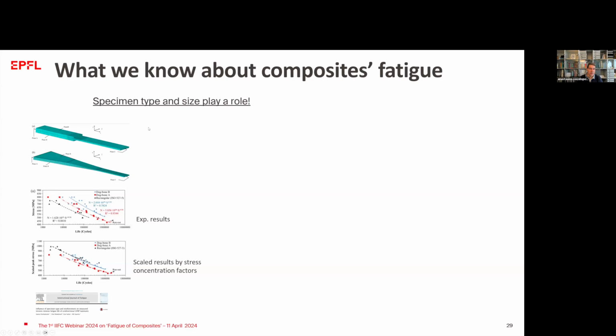We discussed also before about the specimen type, and we know today that there is an effect of the specimen type. There are standards saying that the specimen should be rectangular. There are investigations doing dog bone specimens, finding, for example, in this paper from the group of Paul Bronsted, that there is an effect if you use different types of dog bone specimens. They found better behavior compared to the rectangular specimen in fatigue, and they scaled the results by considering the stress concentrations that they had.